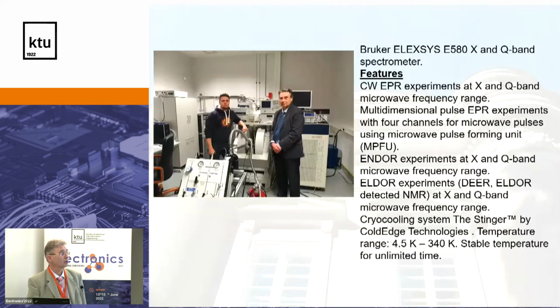And also another powerful tool which we have is EPR, electron paramagnetic resonance spectroscopy. The difference from the dielectric spectroscopy is that when you measure the interaction of an external electromagnetic field with the material, you have the complex answer of the material. You cannot distinguish what's going on inside the lattice, inside the material. And with EPR, when you measure a spin, it is very sensitive to local surroundings. Due to that, you are getting information locally inside the lattice, what is going on, what structural changes with temperature are happening. And for EPR, we also have ENDOR, electron nuclear double resonance, ELDOR,